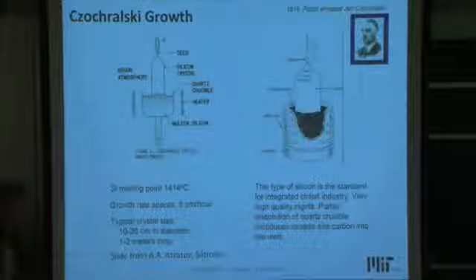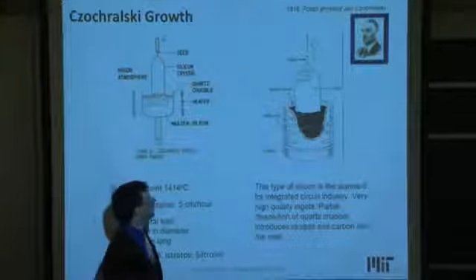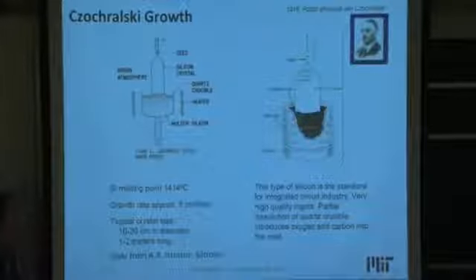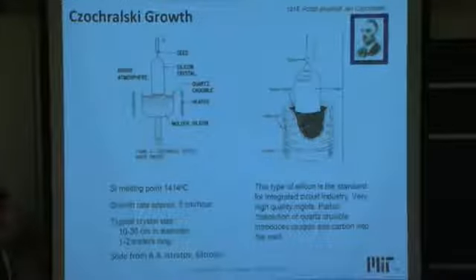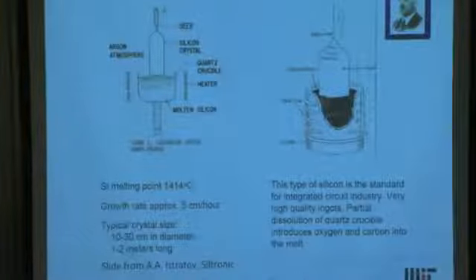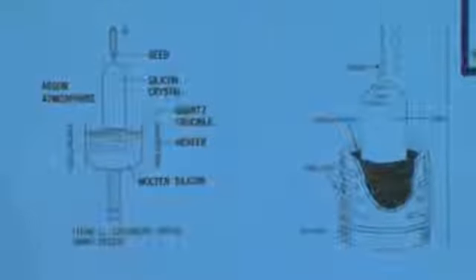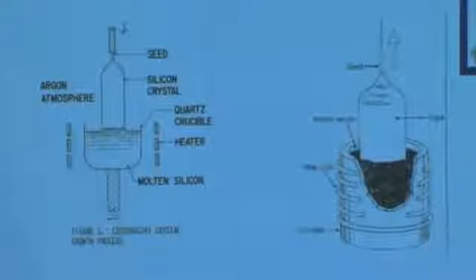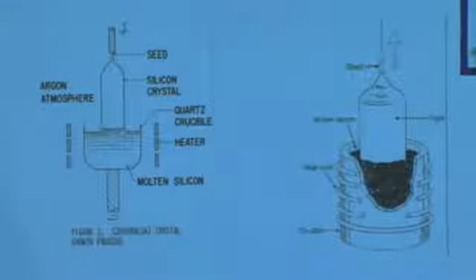The biggest growth method by far is called Czochralski growth, named after the Polish physicist Jan Czochralski. What you do is you have a bath of molten silicon, a crucible, if you will. This tends to be a circular crucible, rounded at the bottom, usually made of quartz, with heaters on the outside to heat up the silicon chunks in here. Once everything is molten, looking like a big bathtub of silicon, you introduce a small crystalline silicon seed into that molten silicon. And then you begin pulling while rotating that seed.